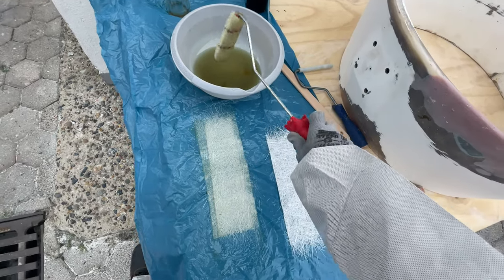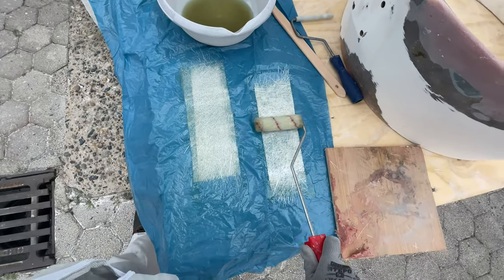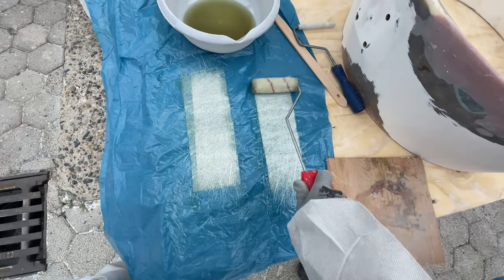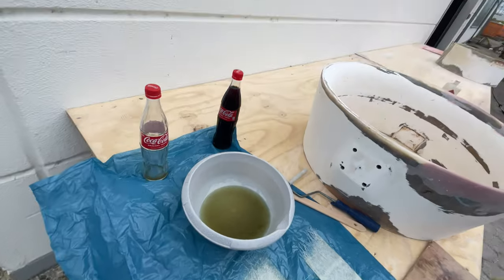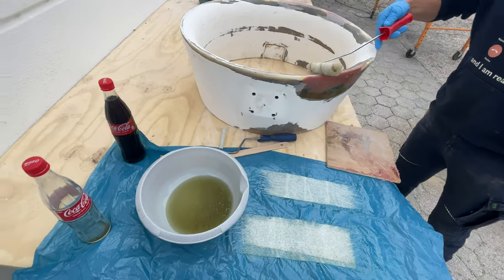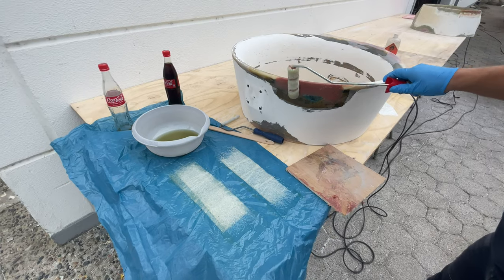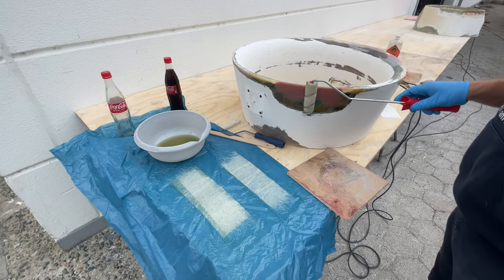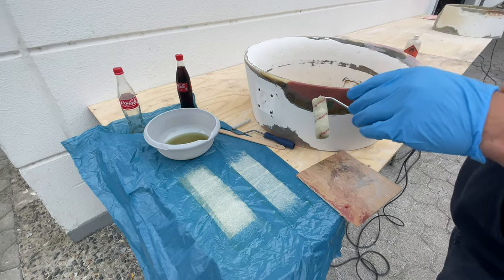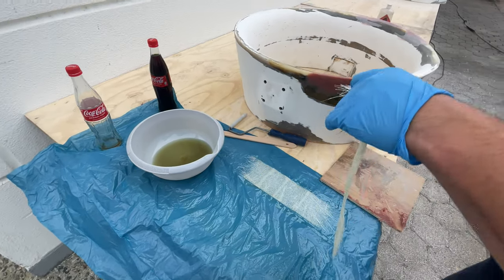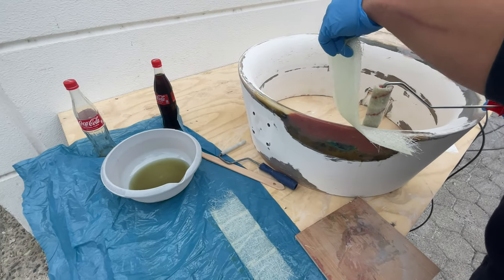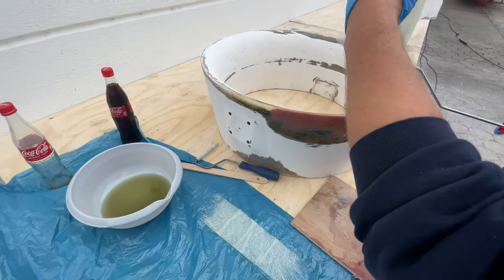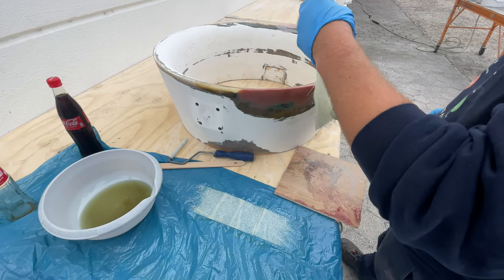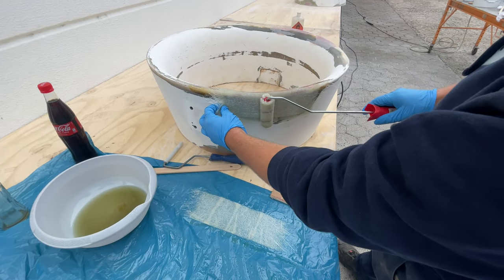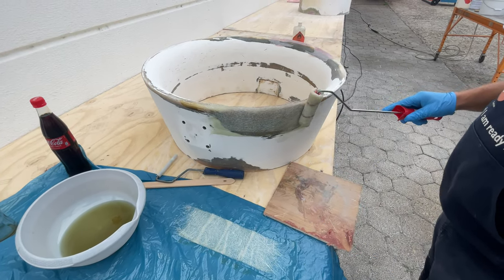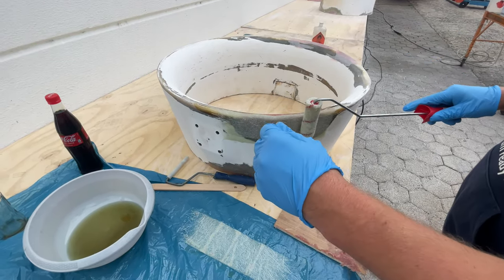The mats they're using are 450 grams per square meter, which is more than the typical boat building fiberglass that you get, but they say it's much better to work with, and you're much quicker because you don't have to put on as many layers. They always work in double layers, so they never put a single piece on top of it. So basically, you put one piece down, you put some polyester resin over it, then you put another piece on top of it, get both soaked with resin, and then put them onto the part and laminate them on.